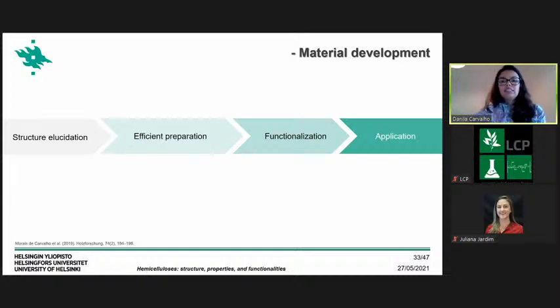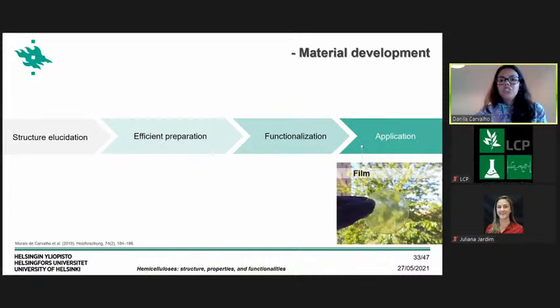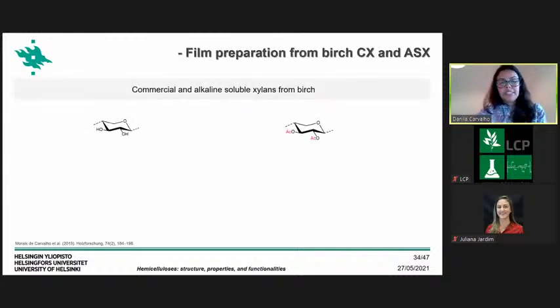And then, in the continuation, what we wanted to do was test some application for the xylan that we prepared. And in this application, we used film formation. For the film formation, we used the xylan from birch. And we used both the commercial xylan and the xylan that we prepared using the alkaline treatment. We cast the films from the non-acetylated xylan in water.